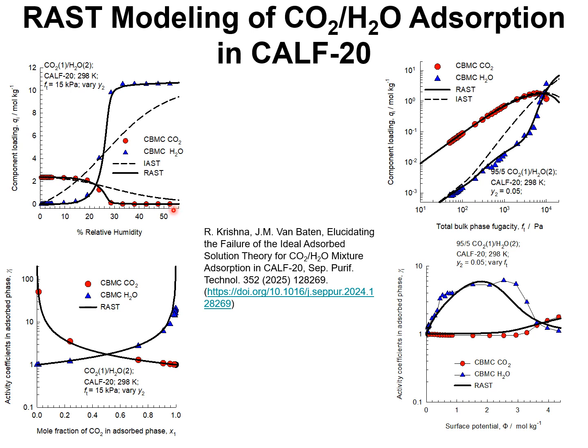In a different set of CBMC simulations, the bulk fluid phase mixture is at a constant composition of 95% CO2 and 5% water, and the total fugacity in the bulk phase mixture is varied from the Henry regime to values approaching pore saturation.